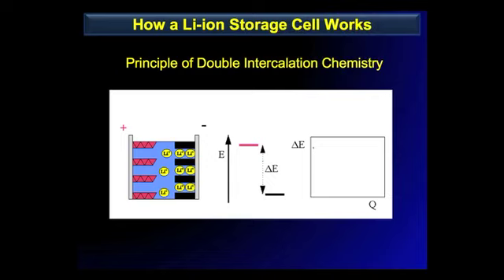So in short, while you watch this thing cycle around, I will explain that no longer, at least in a commercial lithium-ion cell, do we have lithium metal. So this is the negative electrode, which is a carbonaceous electrode, which replaces the lithium, and a positive electrode, which intercalates or incorporates lithium at a high redox potential versus the negative electrode. So during the process of discharge, the lithium ions enter the positive electrode, and during the process of charge, they enter the negative electrode. And so the lithium ions shuttle back and forth between these two host materials.